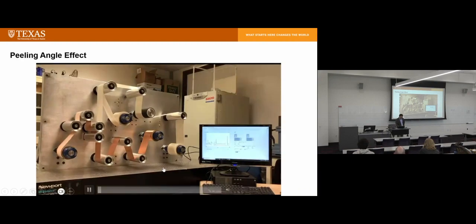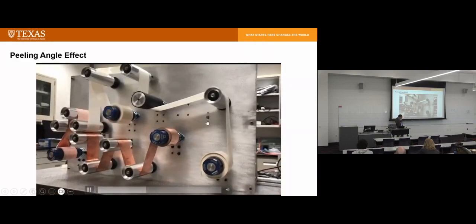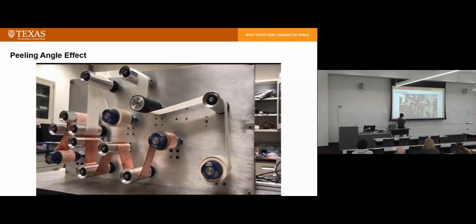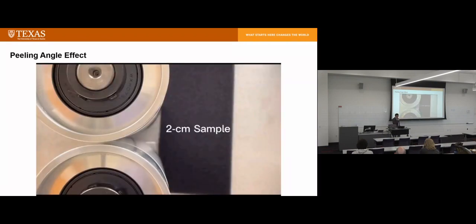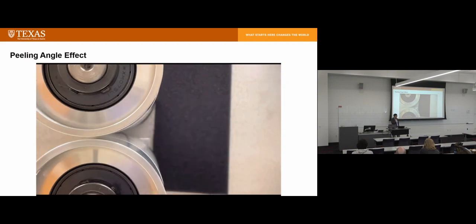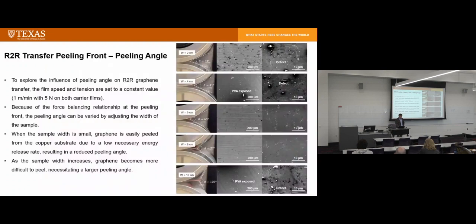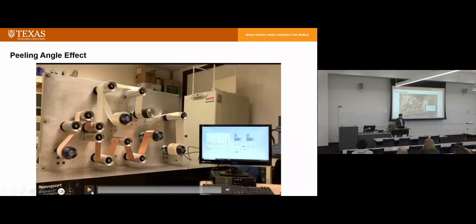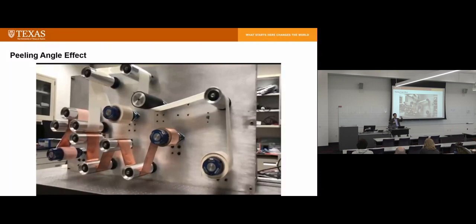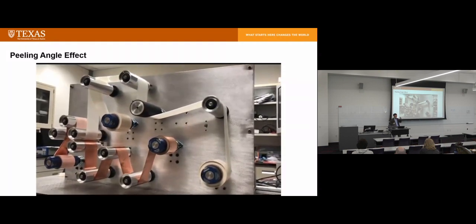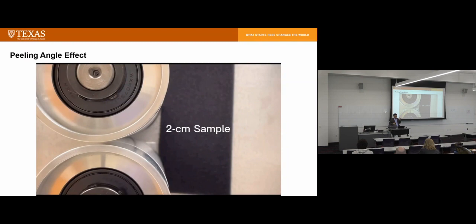So this is a video showing the actual transfer process. The reason I show this is to introduce the peeling angle effect. The first sample we peeled is a 2 centimeter sample. And you see it's effortless, right? The peeling front doesn't move a lot, and the width of the sample is 2 centimeters. So it's peeled very easily.